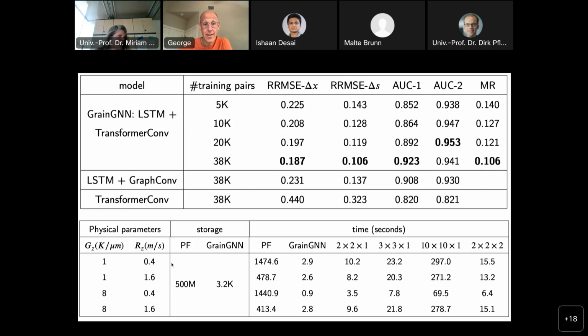And these give you an idea of the costs. The phase field simulation requires about 500 million unknowns and about 20,000 time steps. And it takes, for this regime, a little bit less than half an hour, whereas grain NN takes just 3 seconds. And this is when we scale it to the domain without retraining. These are larger domains, with a larger number of grains. It scales linearly in the inference.